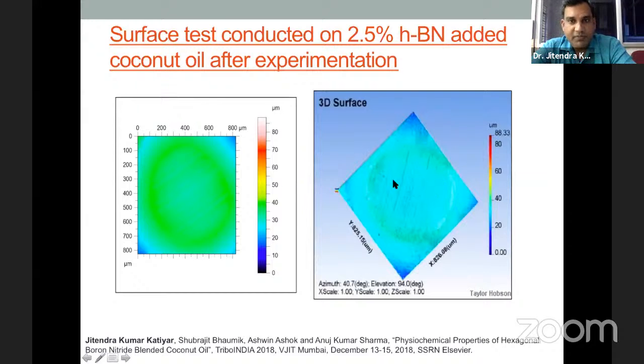And because of that reason, I just check it after I use the 2.5% hexagonal boron nitride in coconut oil and I perform the 4-ball test strip. And we just observe the surface roughness and we get a very smooth surface. You can see in the 3D image the smooth wear scar in that particular sample by adding this concentration.